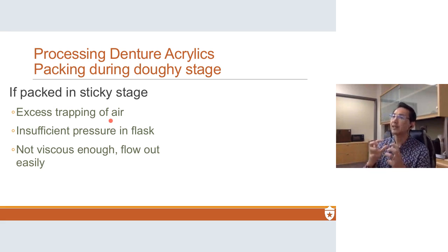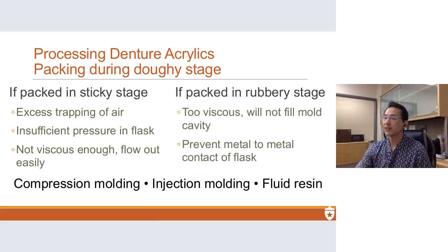mass or mechanical property of that material to be able to push back against the flask, okay, and cause that pressure. You need that pressure because you mix it and you're going to get porosity. So when you flask it, you have to put the pressure on it to get rid of the bubbles. Okay, but you don't get enough pressure in the flask because it's too weak. Okay, and it's also not viscous enough, and it could flow out from the sides, and then now you're going to have gaps in between the stone and the denture. Okay? So you get poor dimensional accuracy there.